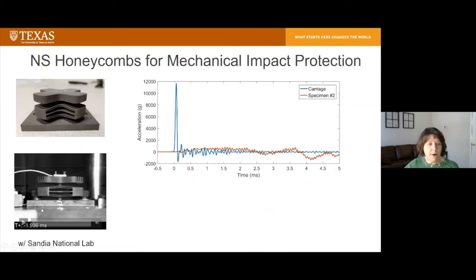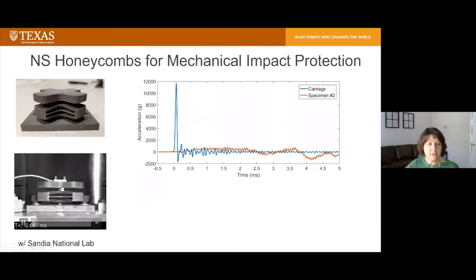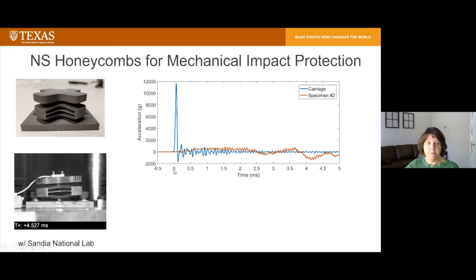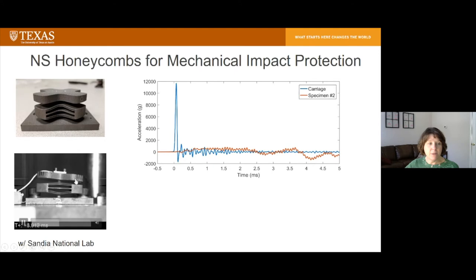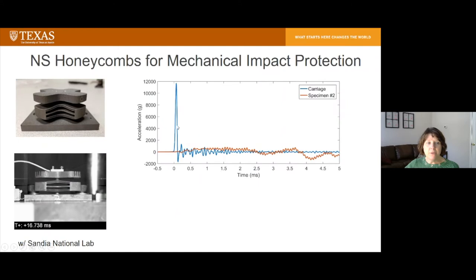We've also done some work to look at isolating mechanical systems, and this is work with Sandia National Lab. You can see this is a very, very large mechanical impulse. So this is a 12,000 G impulse that this particular element is experiencing on an impact testing rig. And that would be the equivalent of basically dropping something out of an aircraft and allowing it to hit the ground. And so in blue, you can see what the carriage, which is what the element is riding on, is experiencing, that 12,000 G's.